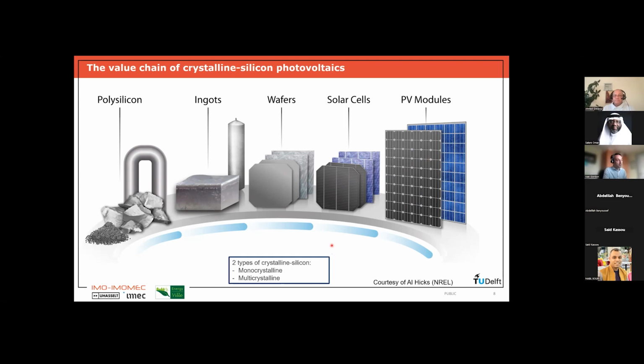And traditionally, 2 types of silicon wafers have been used. We have monocrystalline silicon wafers, where the whole of the wafer has only one crystal orientation, so it's one large single crystal. And with this, you can reach very high efficiencies because it's a very pure material with not a lot of defects. But in the past we were also using so-called multicrystalline silicon wafers. These are wafers where the wafer has different crystallographic orientations. That means you have different grains of different orientations, some grain boundaries. And typically you also have more defects in this material. But it was used a lot in the past because we could make these multicrystalline silicon wafers cheaper than the monocrystalline silicon wafers. And therefore, it also made sense to use those. But I will show later that at this moment, almost no multicrystalline silicon is used anymore.